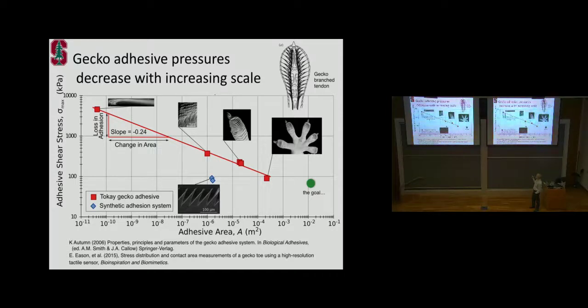So if you do an individual gecko setal stalk, you get actually a quite high adhesive stress, mainly in shear in this case. As you go to a group of stalks, one lamellar clump, it actually drops. What they were able to measure drops quite a bit. And as you go to a whole toe, it gets even lower still. And as you go to a whole foot, it gets even lower still. And oh, by the way, if we want to get to human scale, this is our goal. It's the green dot here. So in that sense, the Cambridge guys were correct. You'll never get there if you want to do human scale climbing. What you need, therefore, is a way to scale your adhesion up to larger areas without sacrificing its performance.